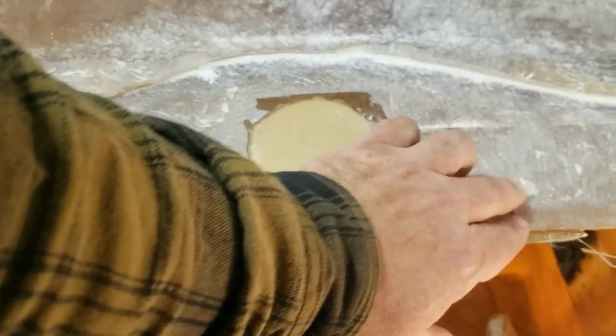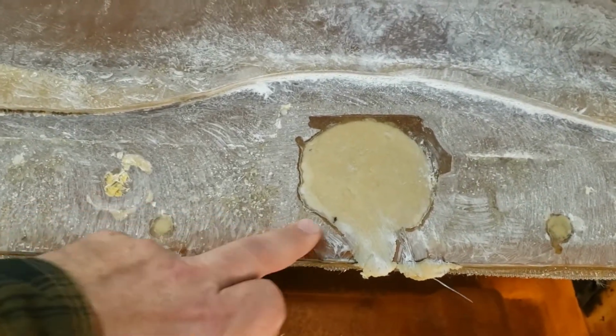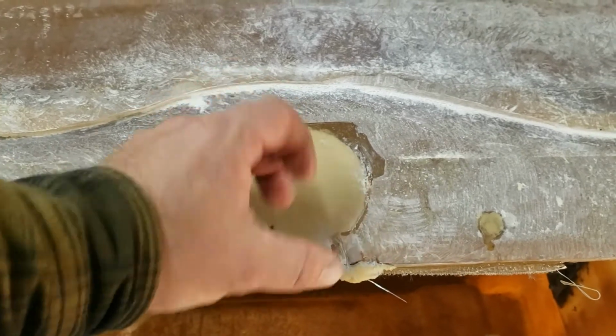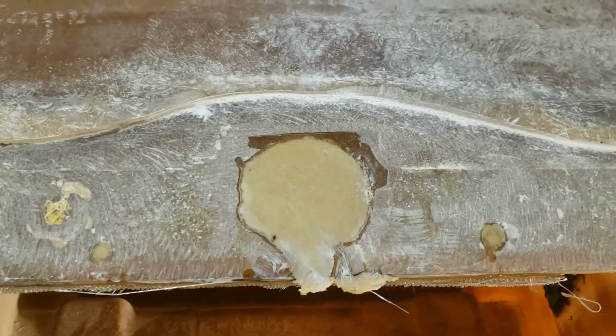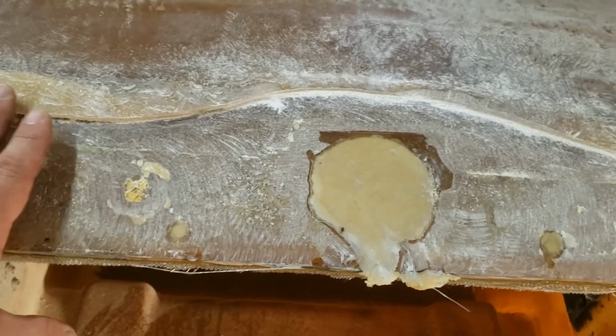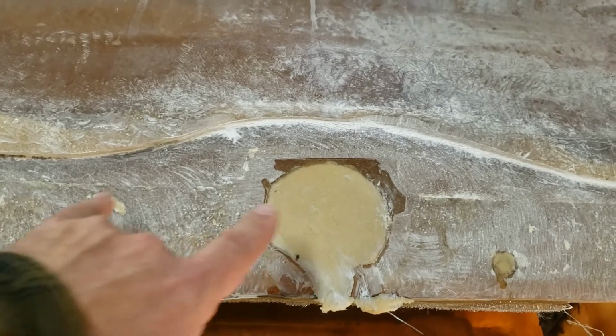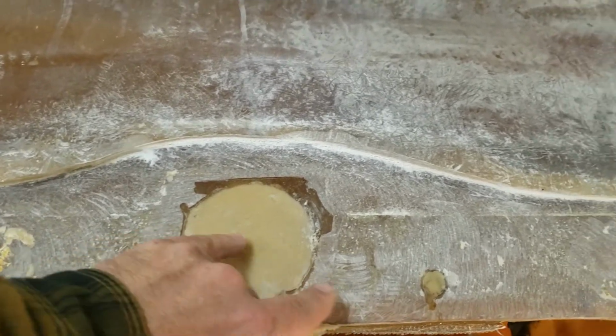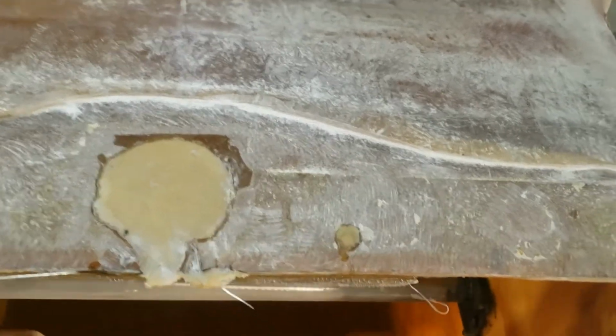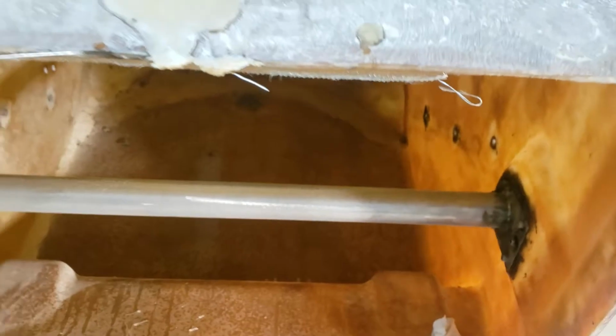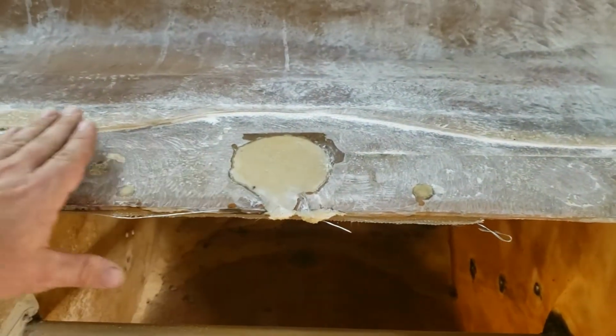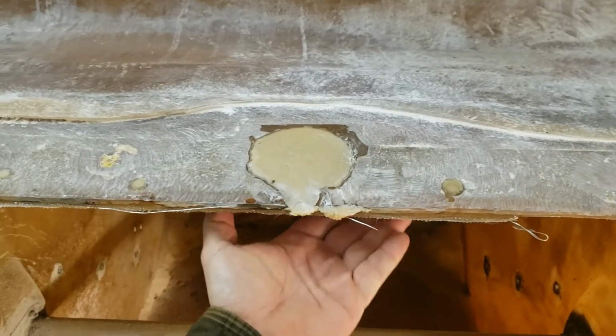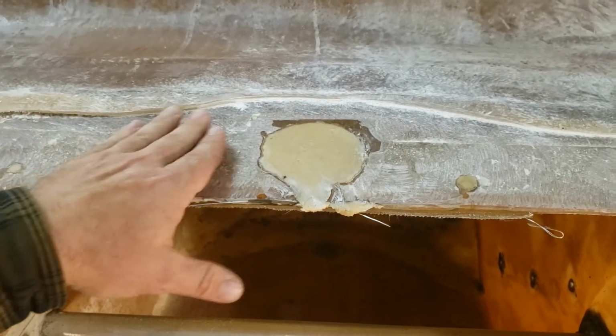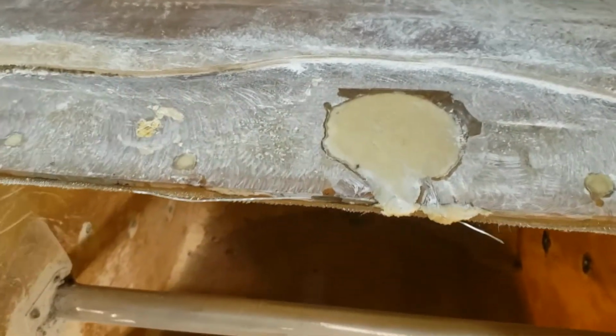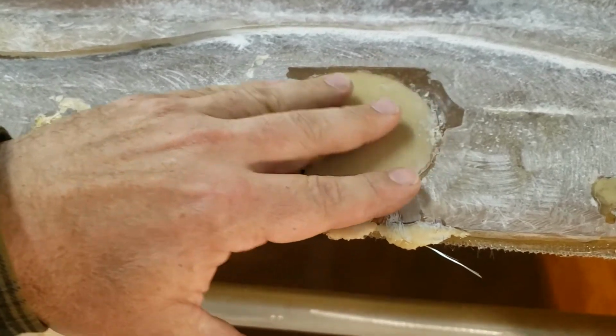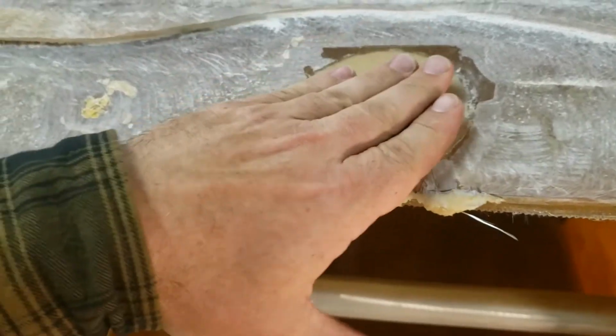I've already done one patch here. There's a couple bolt holes somebody put in the tank to stop leaks, and there was a big fill pipe coming in here that had blown out and actually cracked the fiberglass and did a lot of damage. So the first thing was to fill these holes. I'll back you up a few steps later, but as far as the repair goes, fill these holes with microfibers and resin or epoxy. And then I had some mold release on a piece of aluminum clamped here, and I did my layup from the inside. You can see the mold release with a piece of aluminum left this surface relatively flat and very clean, not full of pinholes or air holes or voids. So it's a nice structural repair.